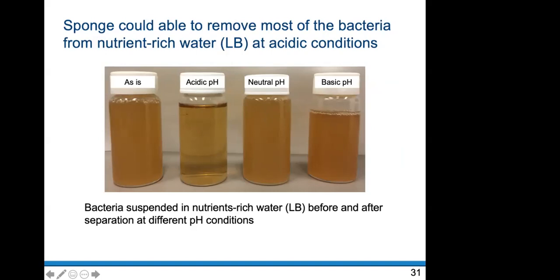So this is the nutrient-rich water I mentioned, where this color represents the protein itself. And if the bacteria are in there, it looks more turbid. For example, in this control case, all the bacteria remain in the water, so it looks very turbid. But at acidic condition, because these particles are removed from the protein, it looks more transparent. And again, at neutral and basic pH conditions, it is a little more turbid. Here I showed only one control, but I did these control experiments at acid, neutral, and basic pH conditions, and they all have a similar high turbidity.